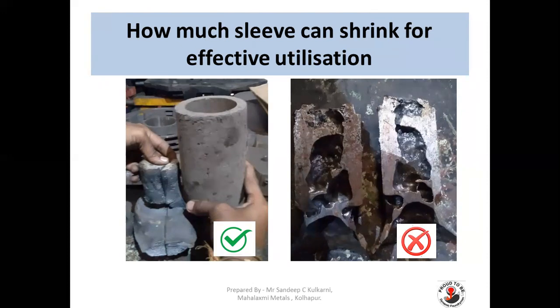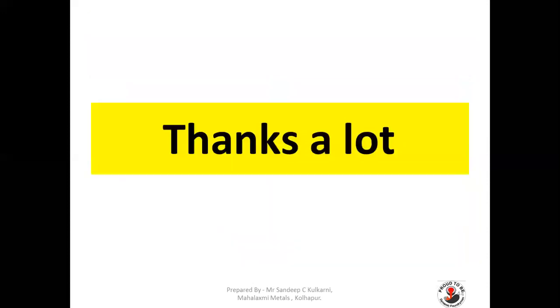On the left you can see a feeder cut down almost totally drained out — this is not recommended because a totally drained riser may cause casting defects. Try to avoid such heavy drain-out feeders; it means your feeders are insufficient and you have to increase the volume of the feeder. That is why it is very important to calculate the volume of your metal requirement first so that you can select the right size feeder for that particular section. Thank you very much for your patient hearing — hope you enjoyed this video.